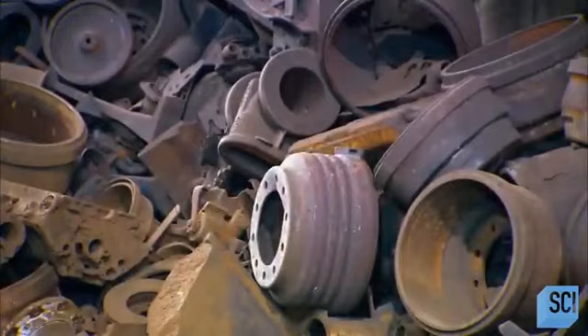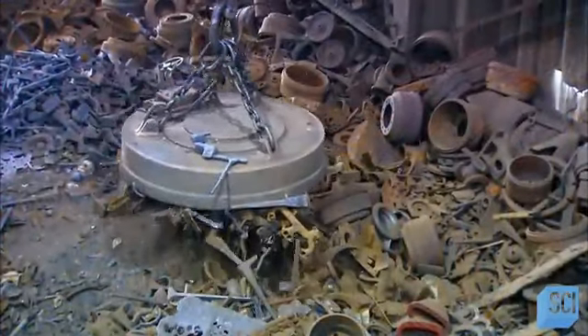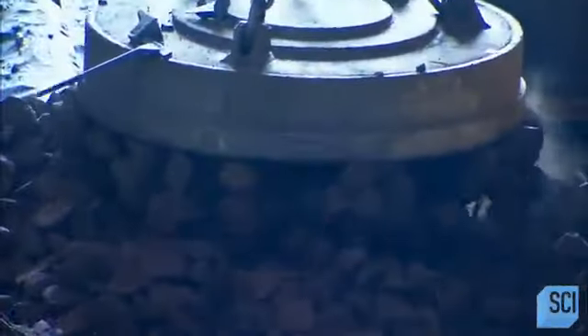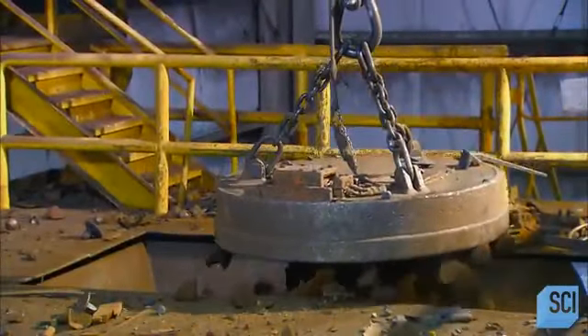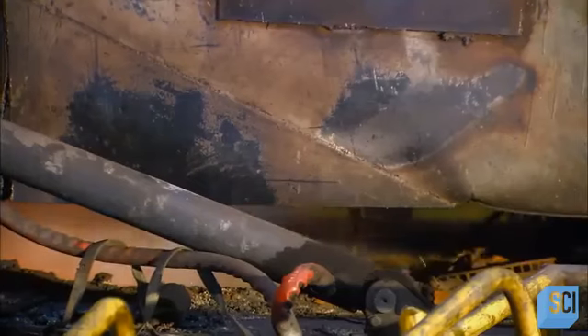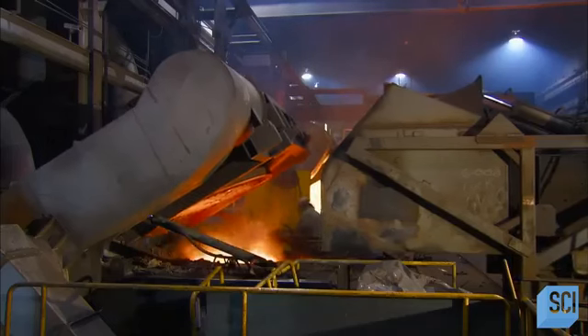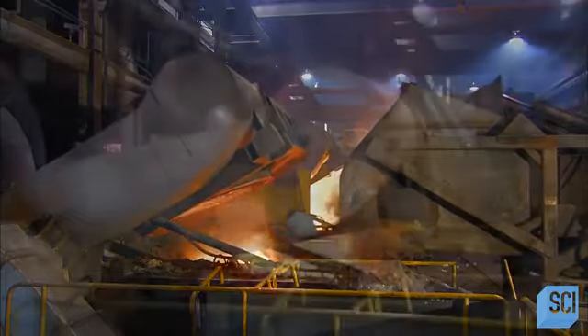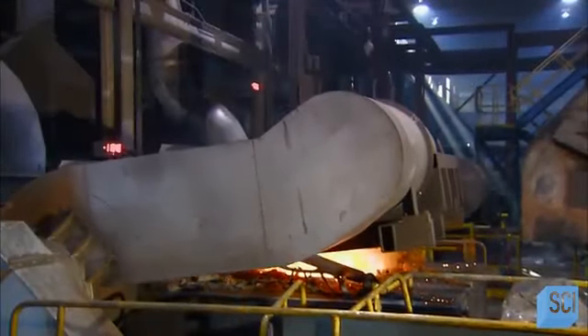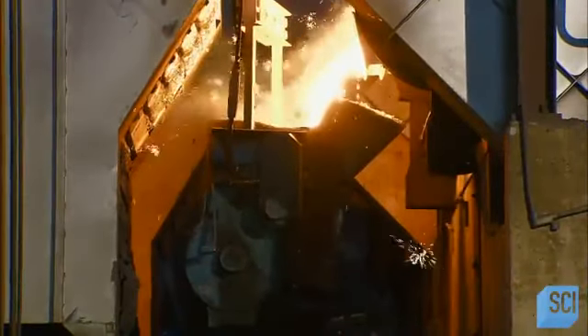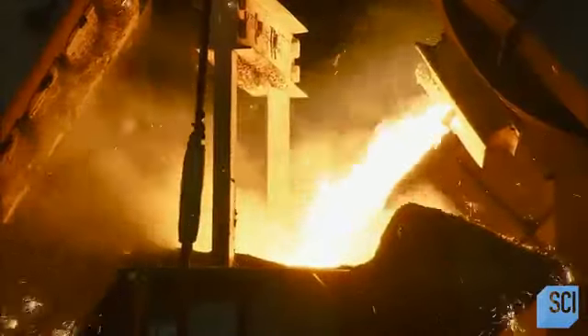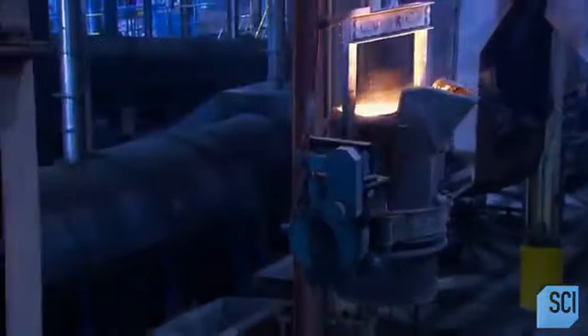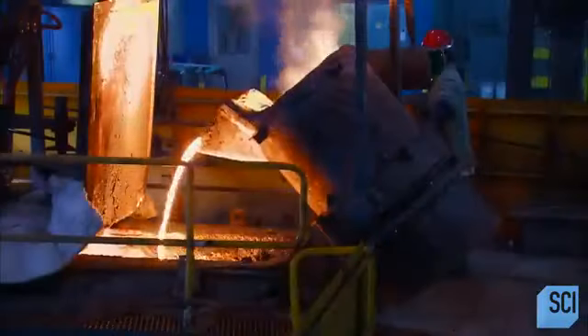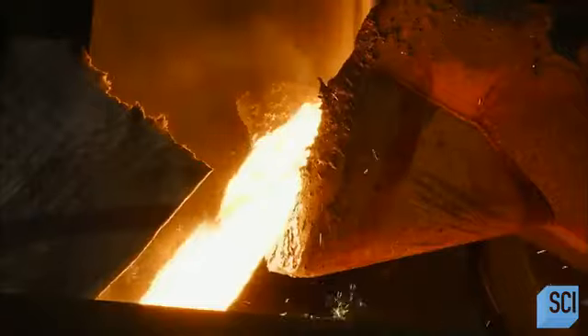The hydrant making process starts with recycled scrap iron, along with steel and raw iron. Using a magnetic crane, workers load the metals into a furnace and melt them at 2,800 degrees Fahrenheit. This turns the scrap metal into molten iron. This super hot mixture is transferred into a remote-controlled ladle and emptied into an automated pouring system.